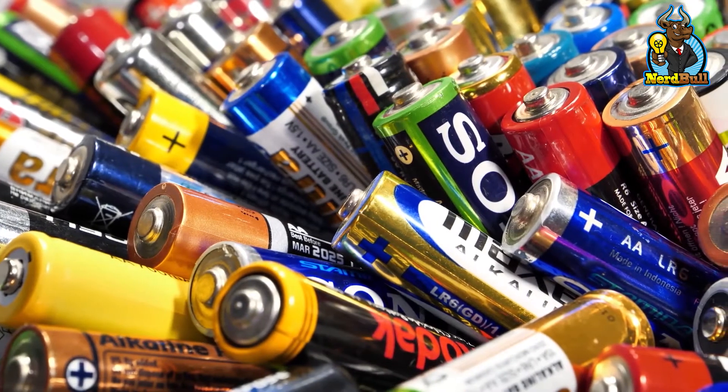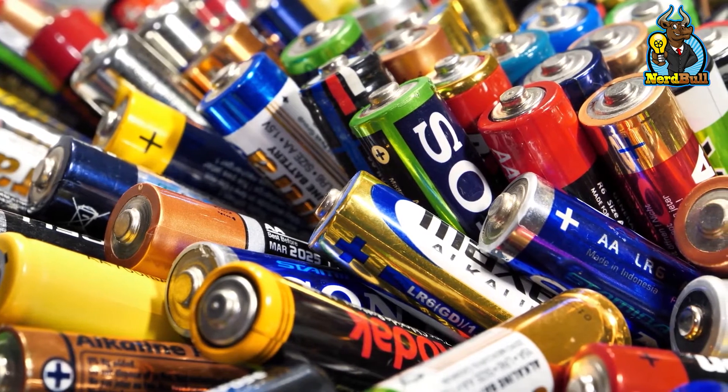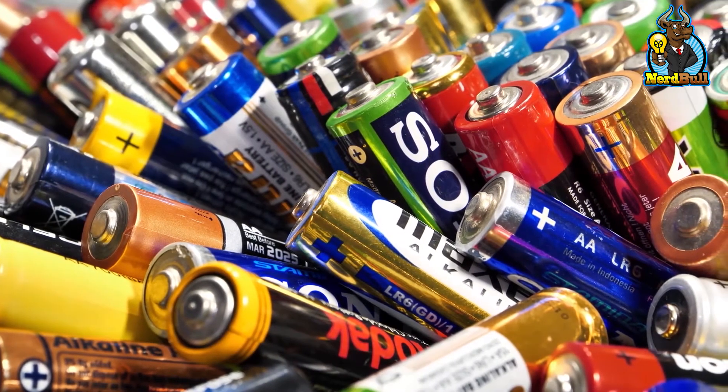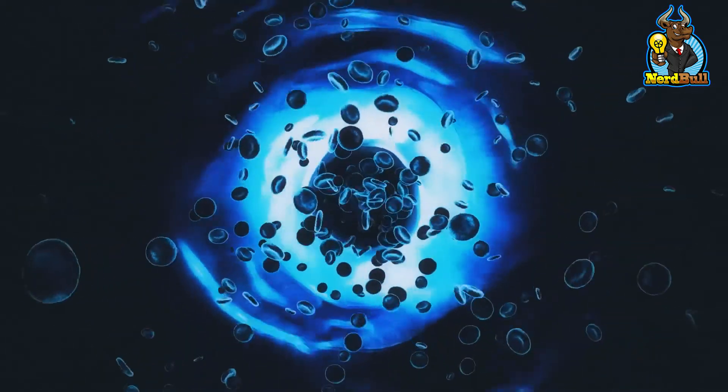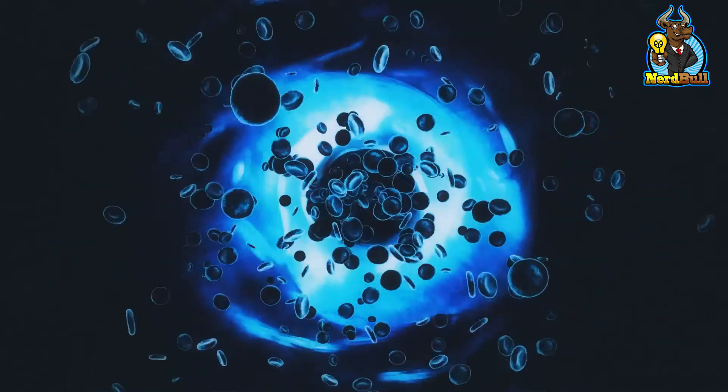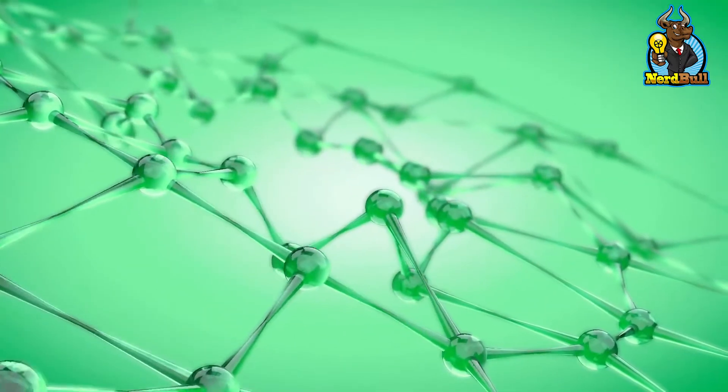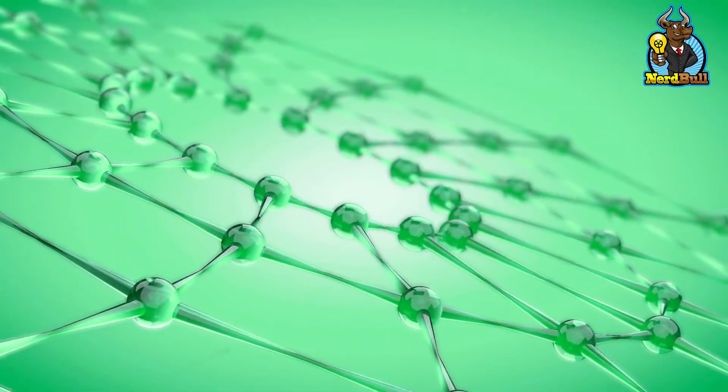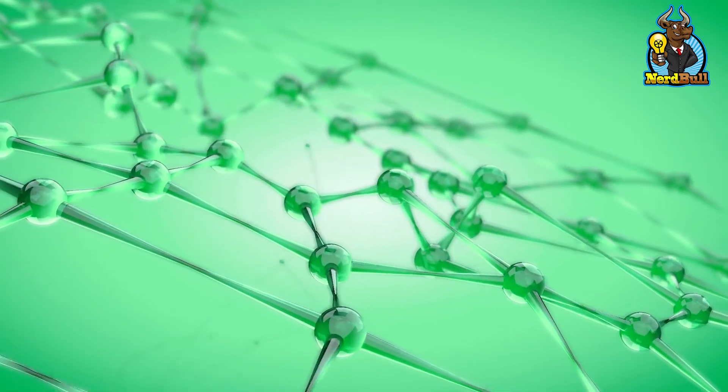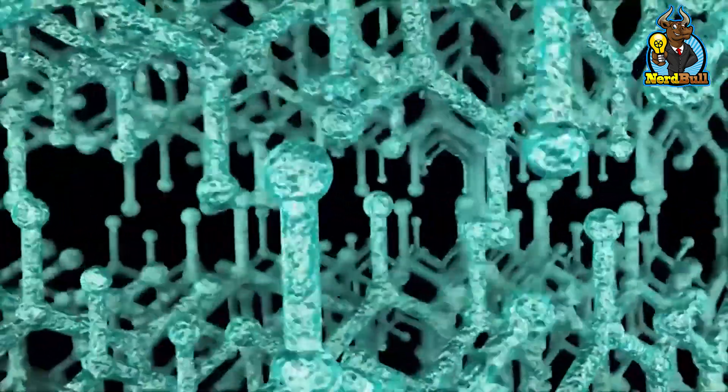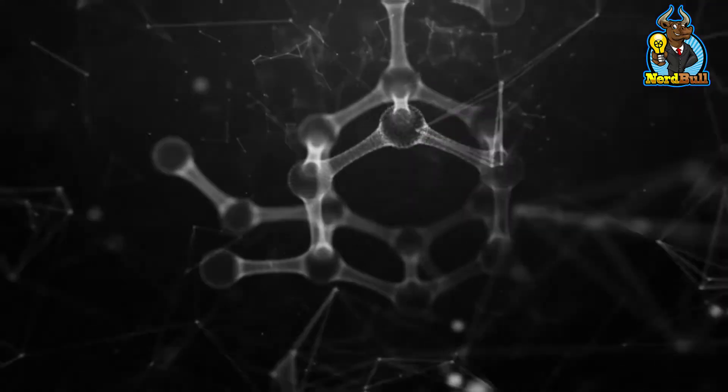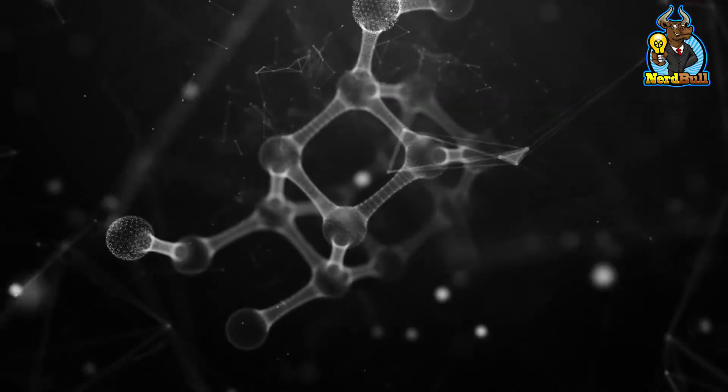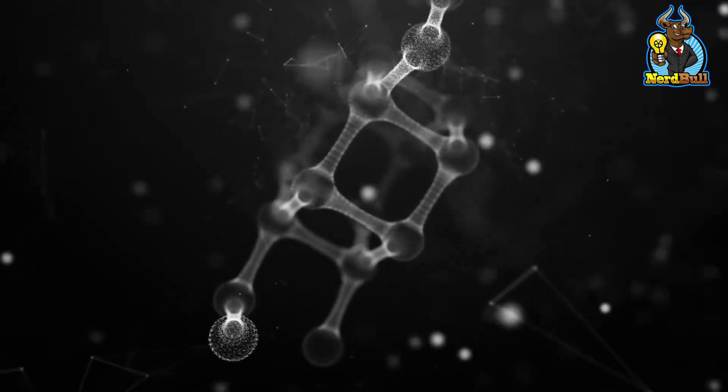Because of their chemical nature and size, common batteries are unsuitable for use inside the human body. Biofuel cells house themselves within the body and use only inserted electrodes. One of the most recent biocathodes is made up of an enzyme surrounded by carbon nanotubes that are enclosed in a porous silicate matrix that is deposited on an oxygen permeable membrane. Carbon nanotubes facilitate electron transport from the semipermeable membrane surface.